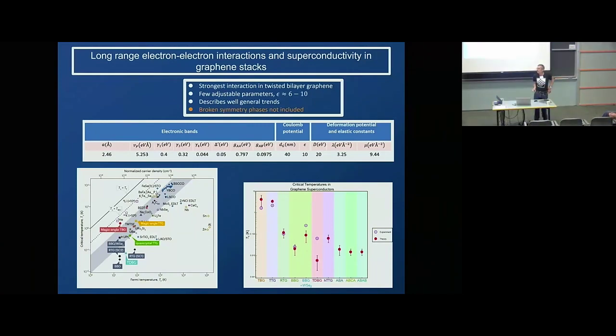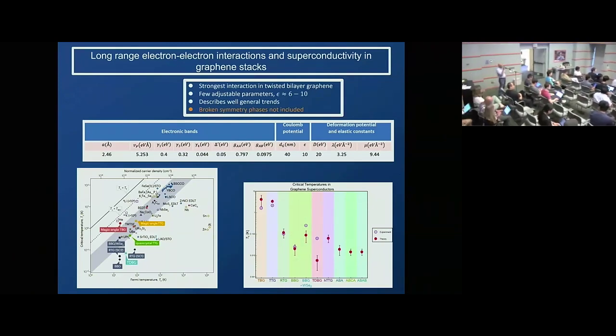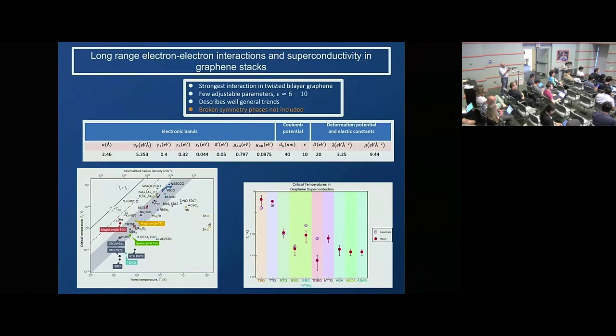But phenomenologically, the normal state in the twisted systems, let's take twisted bilayer graphene, the charge carrier density is not the band structure carrier density. It's very small, it's a deviation from the correlated insulator. And that change happens at very high temperature, much above TC. So then what's the justification for this kind of approach? Same question I asked Shankar yesterday.